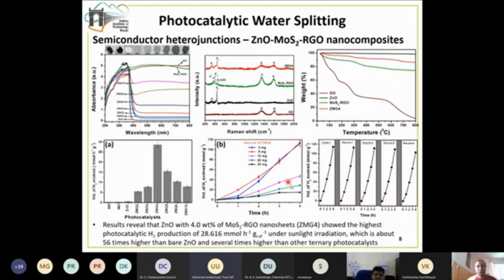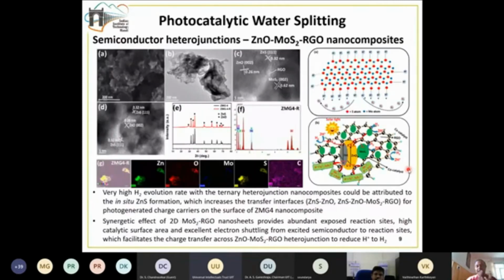We also did the recyclability of our catalyst, this ZMG4, and the catalyst is very stable and it could be recycled for 4 times or even beyond. We stopped at 4 recycles. So this shows the heterogeneous and recyclable nature of the catalyst. Then everything is nicely done.